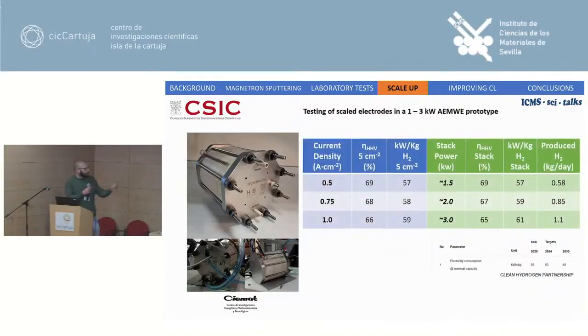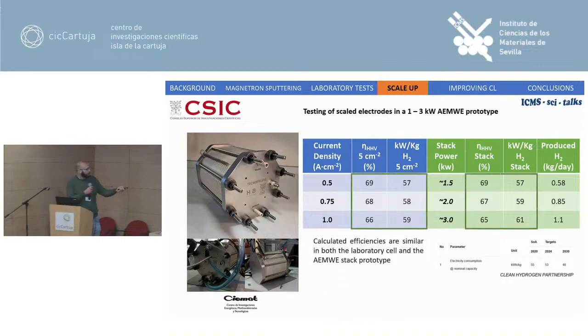So by summarizing, here we can compare our efficiency results. Here are those obtained in our laboratory. Those ones are the ones obtained by the stack, and we can see that they are more similar. And comparing the specific power consumption with the recommendation made by the Clean Hydrogen Partnership, we can see that at low current densities we are near to the recommendation, but we need to improve our catalytic coatings a little bit more. And in this condition we could prove our theory, and we were able to obtain almost or more than 1 kilogram per day at the higher current density rate of working.